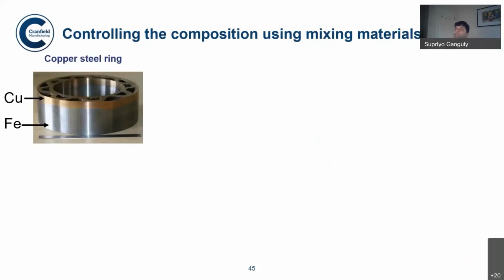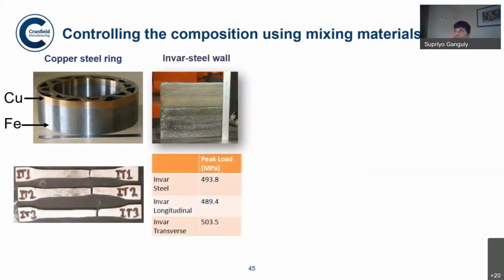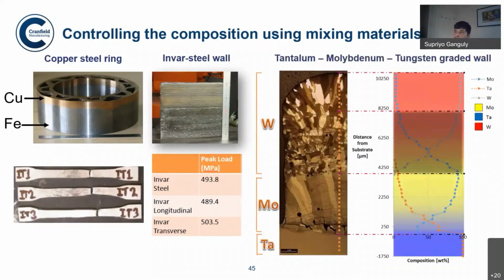So, control of composition with mixing. These are some examples of different types of structures that can be generated. This is an iron copper mixed structure. We can have an Invar-steel wall, where the load carrying capacity increases. One of my students has done some work in the area of refractory based alloys, and a graded structure with tantalum, molybdenum, and tungsten is shown here. This work has been published and you can access it quite easily. It is in the free domain.